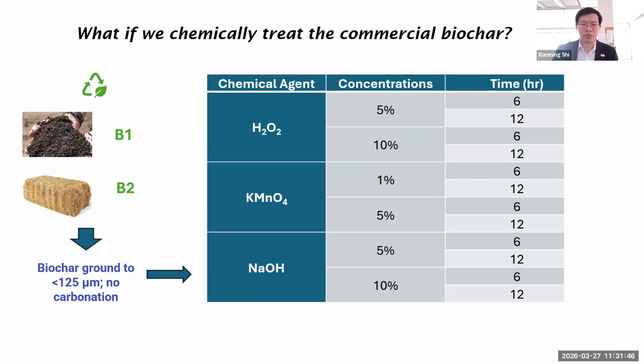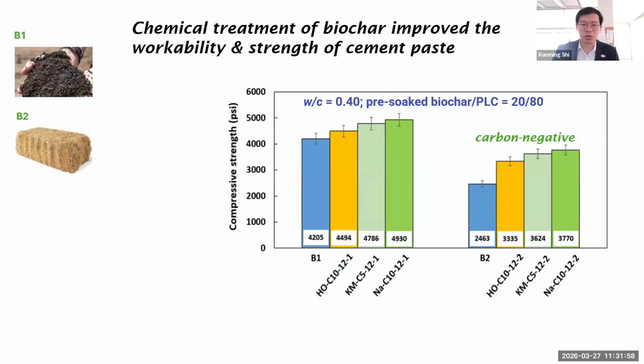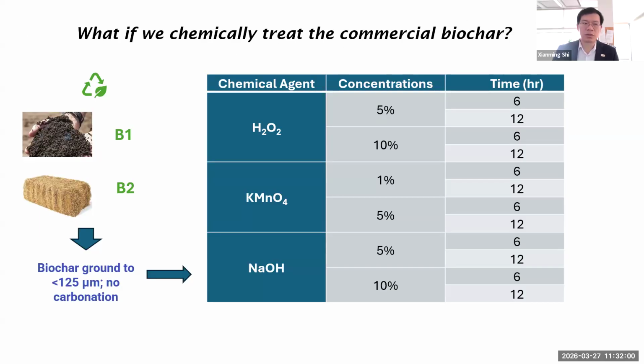So, moving on to some other thoughts. In the same pattern, we found, what if we chemically treat the commercially available biochar? Can we do some magic with it? So we play with two types of biochar, one derived from cow manure, one from wheat straw. And we use different chemical agents. We're trying to induce some sort of surface functional groups such as hydroxyls or carboxyls on the carbon surface.